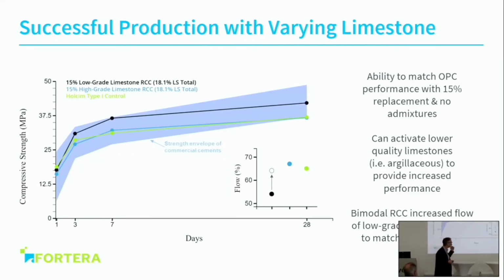So here you see a test with two different types of limestones. You see in green control cement, and you see in blue and black a blend with our product with different quality of limestone. High-grade limestone, which gives similar results as the control cement, and a low-grade limestone, which to our surprise gave even better results than the previous blend.